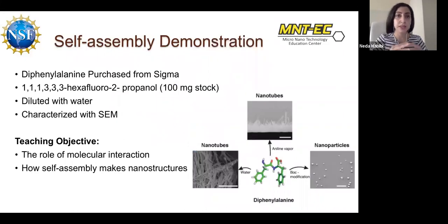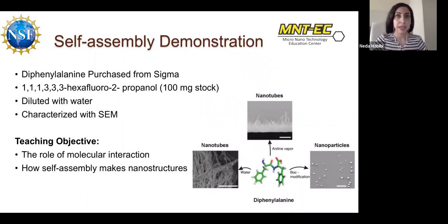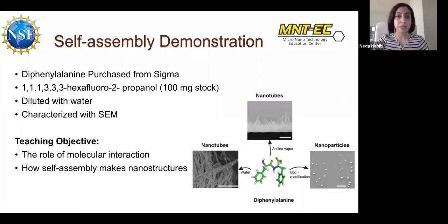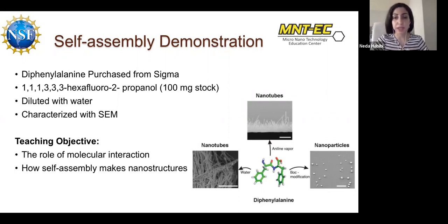For this self-assembly process, we need the diphenylalanine powder, which can be purchased from Sigma or any other company that provides lab materials, and an organic solvent — hexafluoropropanol — in which this peptide can be dissolved. Students can learn why we use an organic solvent due to the hydrophobic interactions of the peptides. Once the stock solution is prepared and diluted with water, the self-assembly process immediately begins and we get nanotubes and microtubes spontaneously. We then put a drop on a support such as silicon and characterize it with scanning electron microscopy to see the tubes forming, including nanoparticles and microtubes.